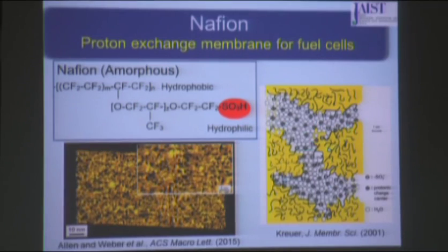Then this is the schematic view. The white is the water nanochannel, relatively 1 or several nanometers wide. The yellow one is the hydrophobic part. This is the microphase segregation. This is a schematic view analyzed by small-angle X-ray scattering. This is the actual view using cryo-electron microscopy, which was very recently published. So the actual view and the schematic view are very similar now. So Nafion is very useful.